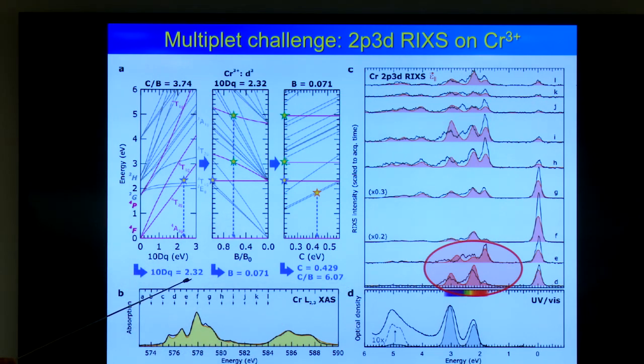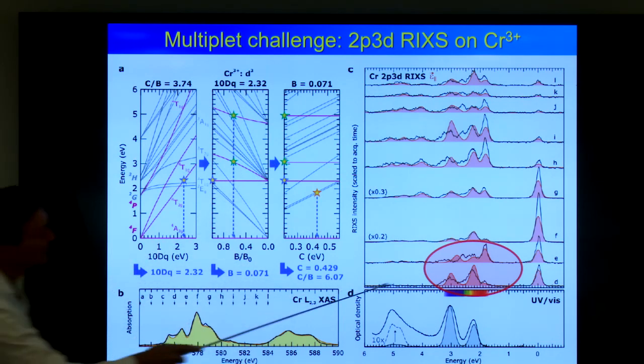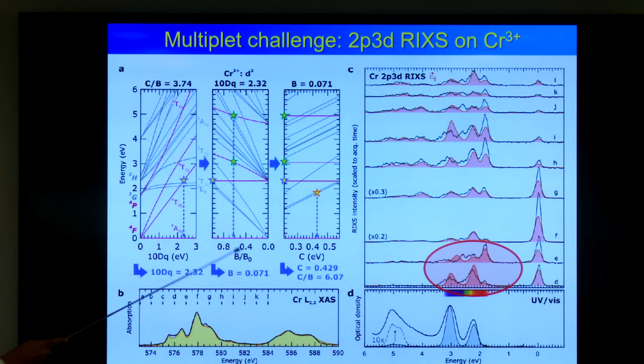Maybe you can even do it in 3 digits, but let's say 2.32 electron volts. It's also the ground state value instead of the final state value. Now you can see here that the other dipole allowed transitions in pink also do not move with Racah parameter C, so you can fix them from this peak. And that gives you Racah parameter B is 0.071.